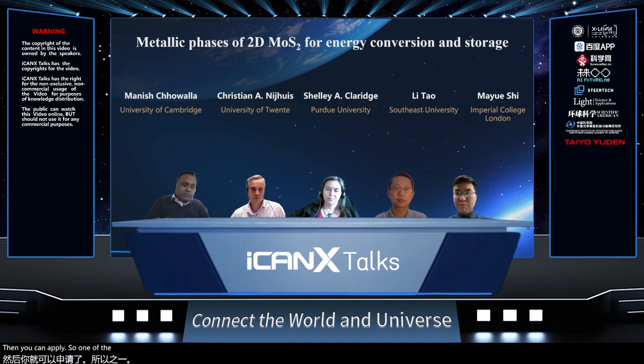Then you can apply. So one of the things that we've done in my group recently, which we hope will come out somewhere soon, is that we've applied those principles of indium and bismuth deposition, this gentle deposition principle, to deposit and make van der Waals contact with even refractory metals like palladium and platinum. You can form the same type of contacts that you form with indium and bismuth with the heavy metals to get P-type devices.